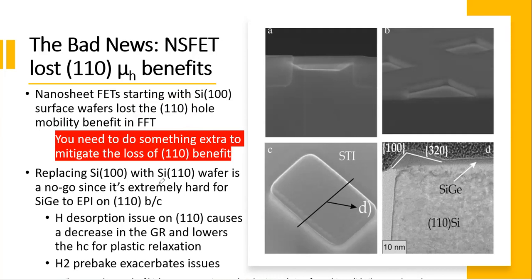Then the question is, can I do 110? I mentioned for CFET we could change the crystal orientation. Well, in theory, you could. But the problem is that it's very difficult to do epitaxial growth on 110. Many people have studied that, and they find the fundamental reason you cannot do that properly is the 110 growth rate is bad, and you easily form many dislocations. The theoretical critical thickness for epitaxy on 110 is very small, much smaller than 100. And then your H2 pre-bake, which you have to do to get rid of the native silicon dioxide, will wrinkle the surface and make defects.